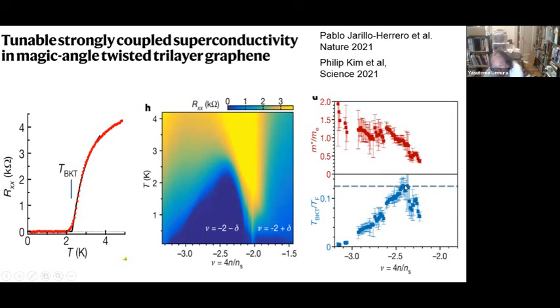This is interesting, but quite odd, in the sense that for any strong coupling or weak coupling superconductor, if you make it very thin, the Kosterlitz-Thouless theory would dictate that the transition should be 1/8 of the Fermi energy scale. And this is happening in this sense only at this particular gate value.